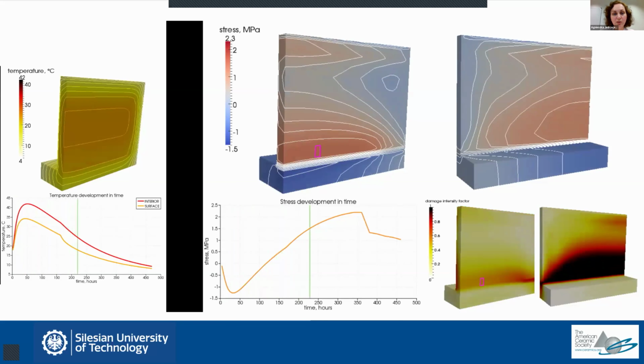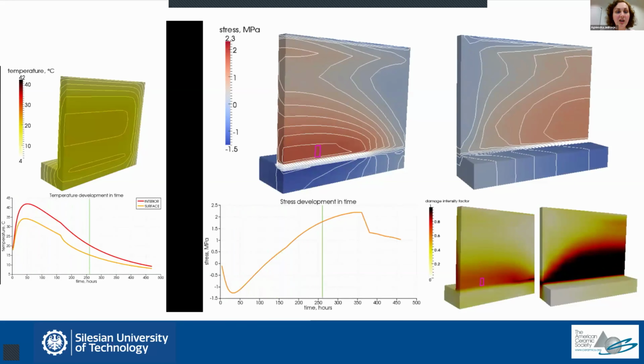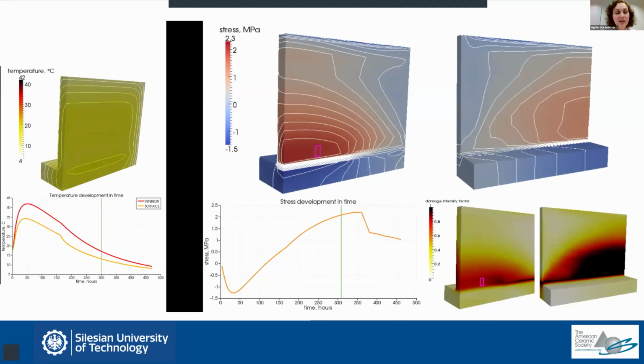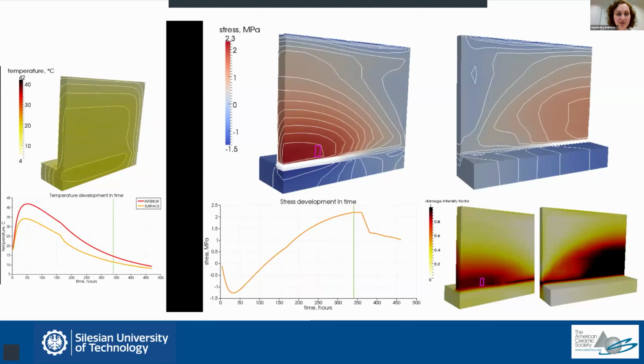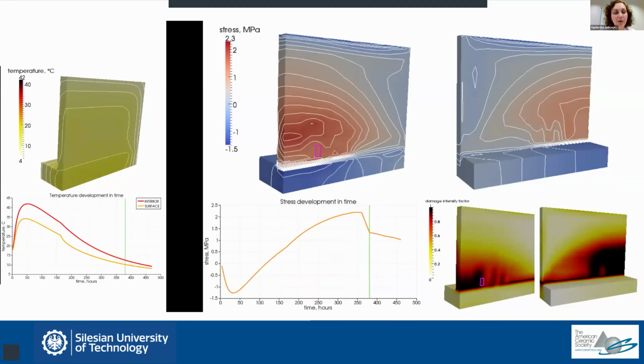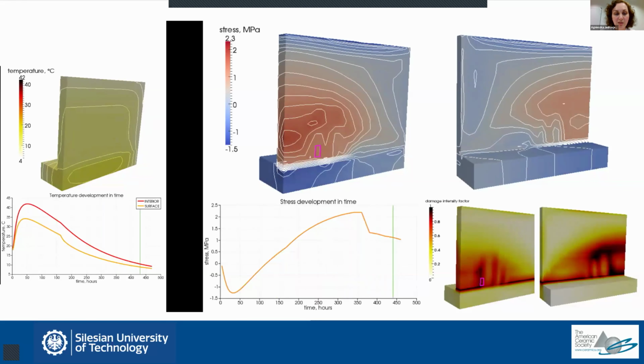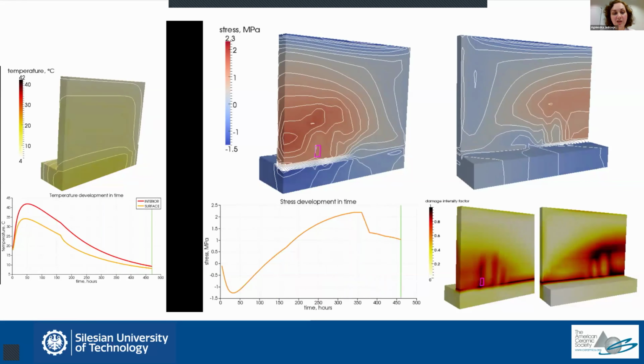And as a result, on the right side of this simulation, you see how stresses change. In the beginning, we observe compressive stresses in the wall. And then as we pass the maximum hardening temperature, these compressive stresses diminish, they cross the zero value, and then tensile stresses start to develop. And in many of such elements, these tensile stresses reach significant values, which reach the tensile strength of the element. And as I explained at the beginning of this lecture, if the tensile strength is reached, it means that a crack is formed.